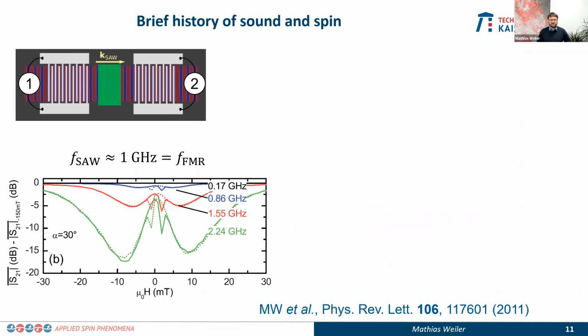In our experiments later, we then showed that if one increases the frequency of the acoustic wave such that it matches the ferromagnetic resonance frequency of the magnetic film, one can then get a resonant coupling between the magnetic excitations in this magnetic film and the surface acoustic wave. So we still see this hysteretic behavior, the switching behavior over here that was shown on the previous slide already, but now additionally, we also see this absorption which occurs, which we ascribe to the interaction of the sound waves and the spin waves at the mutual crossing point of their dispersions.